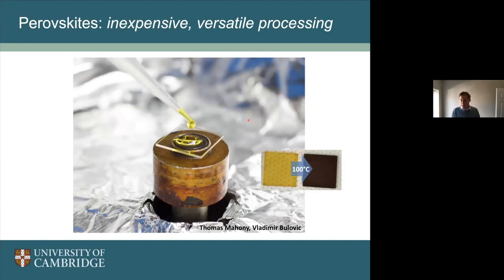The other really exciting thing about it is that we can make it very inexpensive. Into inks, and we deposit them down onto glass substrates. For example, we might spin them very fast, and that makes a very uniform film, which is this yellow film here. Then we heat it quite gently. 100 degrees Celsius is a very gentle heating for semiconductor processing. It forms this really nice crystalline film. It's a very dark absorbing film.